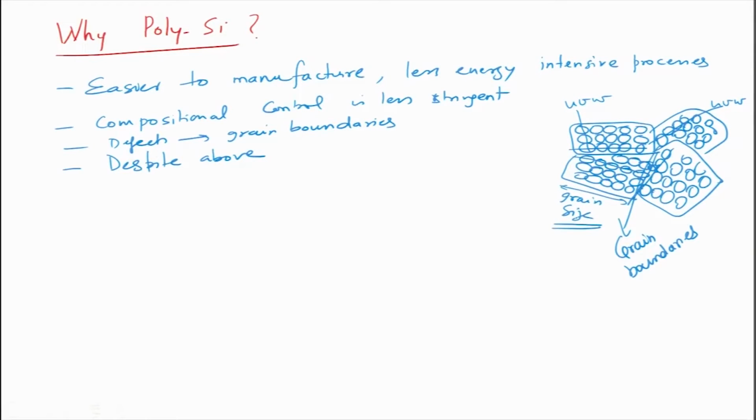In polycrystalline silicon solar cells, generally the grain size is of the order of the thickness of the device or even larger. So, they have big grains, they do not have small grains. So, grain boundary effect is minimized. So, despite the above issues, performance is not very poor.